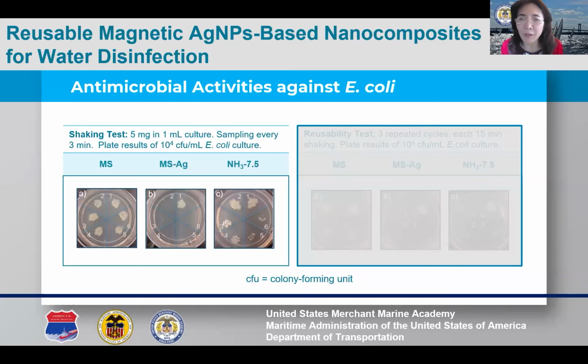In the left side figure, MS showed no change in bacterial count after 15 minutes of treatment, as expected. MS-Ag eradicated all bacteria within 3 minutes, while not as rapid as MS-Ag, Ammonia 7.5 demonstrated an excellent antimicrobial efficacy, reducing bacterial count with increasing treatment time.